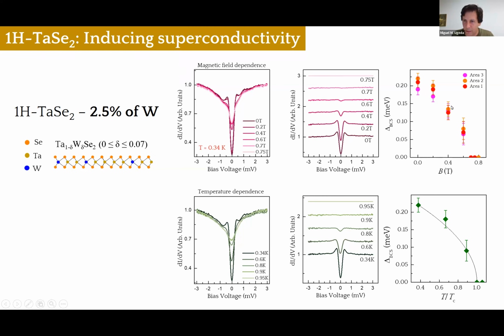So here's the evolution of the superconducting gap, and this is something that we can fit using the standard BCS superconductivity. Here I show you the evolution of the gap with the magnetic field, and the same here for the temperature dependence. At 300 millikelvin we see a dip that evolves with temperature, becoming narrower and narrower and shallower and shallower. We do the same normalization, and we can extract the gap as a function of temperature. So we can extract the upper critical field and the critical temperature for a particular concentration of tungsten atoms.